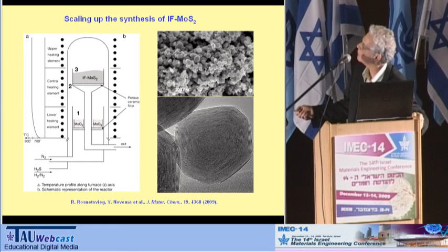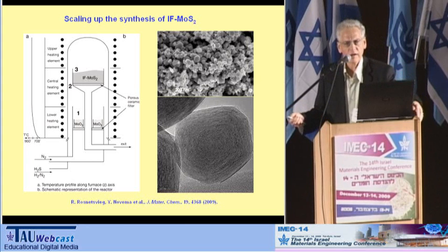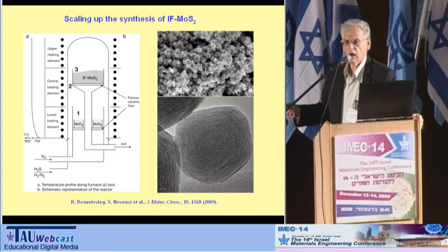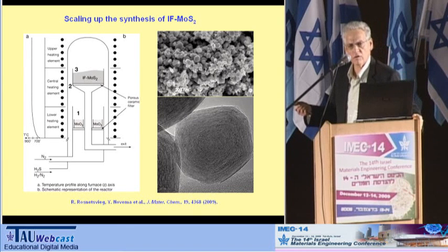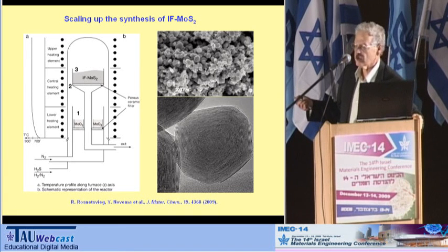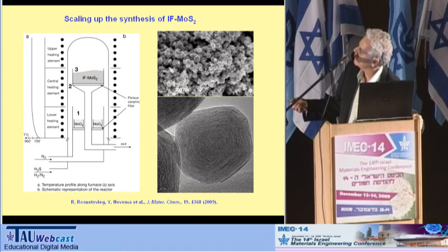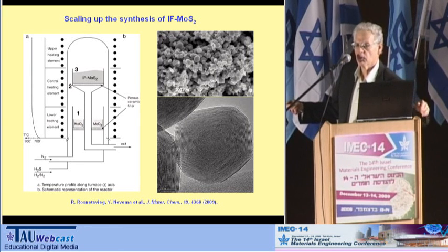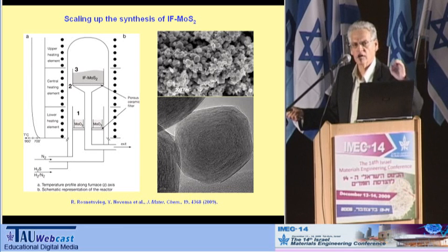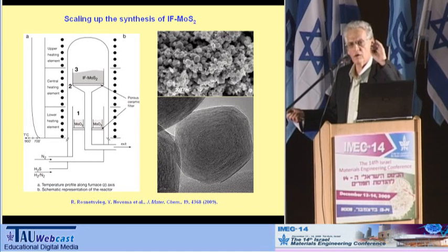I show you a recent publication where we have produced the molybdenum disulphide from molybdenum oxide. This is something that we already did 16 years ago, but now we can do that in appreciable quantities. We take molybdenum oxide, we evaporate it, and then we flush it with hydrogen. The vapor of molybdenum oxide reacts with the hydrogen, reducing the molybdenum oxide to molybdenum suboxide, which loses its vapor pressure and forms nanoparticles of molybdenum suboxide.